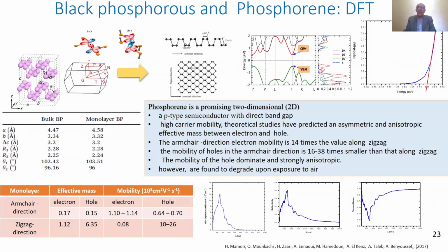But theoretically, using density functional theory, the obtained results confirm what has been observed experimentally and go beyond. First, it shows that the hexagonal structure is a stable one, and it is anisotropic with two directions, armchair and zigzag direction. It shows that it is a semiconductor with a direct band gap, and the optical gap obtained theoretically shows that for a monolayer of puckered phosphorene, the band gap is 2 electron volt. Many other results have been obtained by using density functional theory.